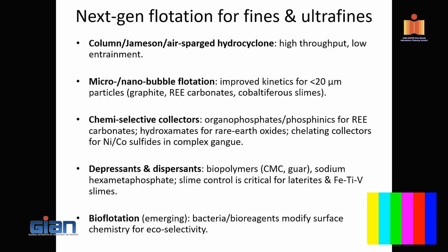So this is where we talk about the entire philosophy that we discussed yesterday: generating the ultrafine, utilizing the ultrafine grinders for generating the fines. Now separation is feasible, provided those particles can respond to flotation. That means we need to look at their characterization with respect to contact angle, hydrophobicity, and all of that, and whether they have sulfide content or not. Because usually most particles having sulfide content have a hydrophobic behavior, except coal. Coal has a different quality.